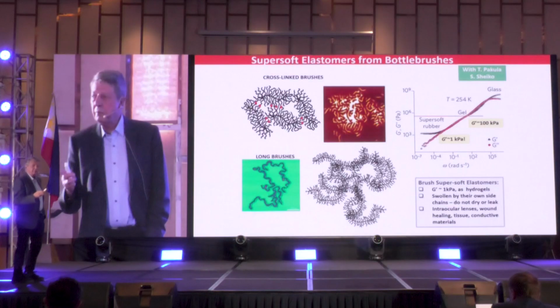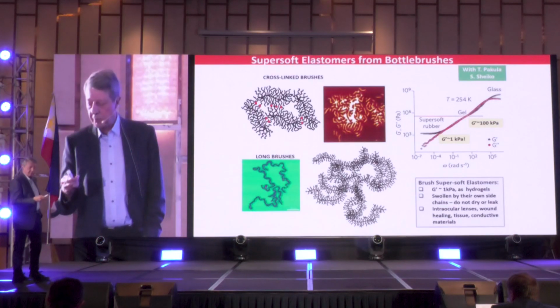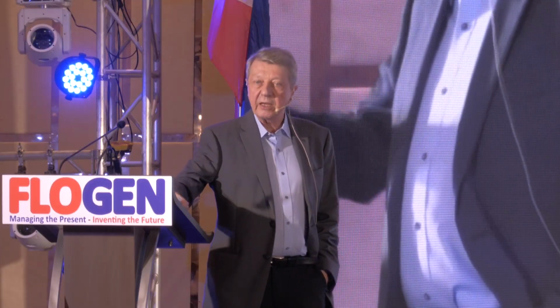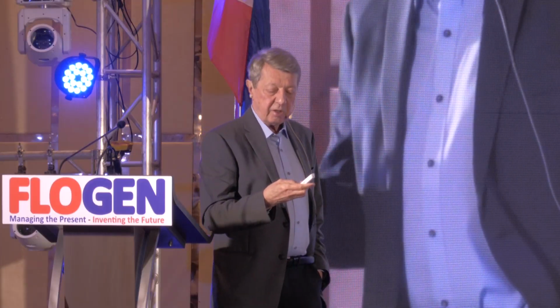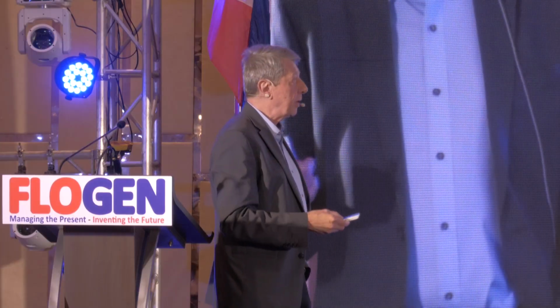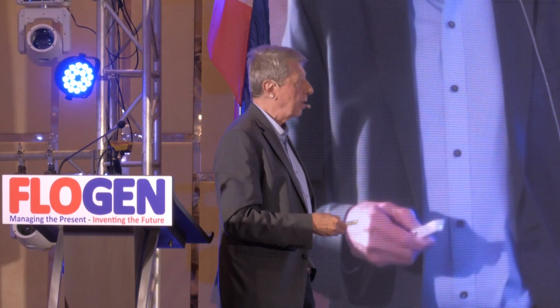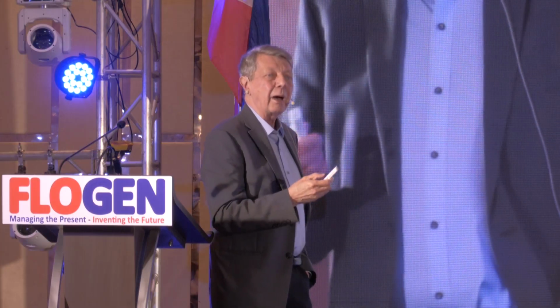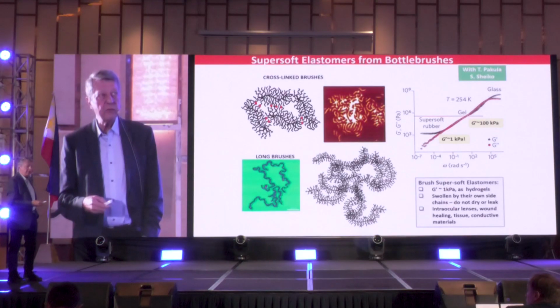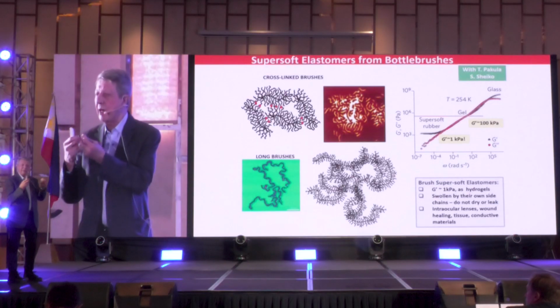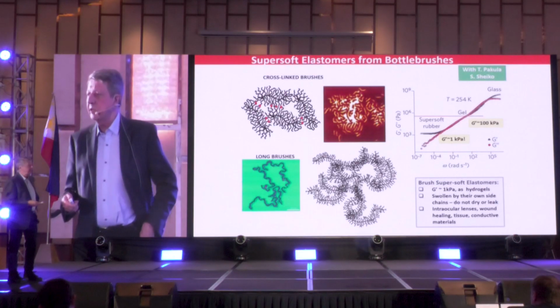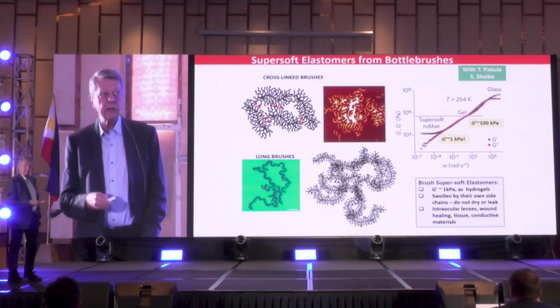So one important issue is the mechanical properties. Every polymer below glass transition is glassy. So it is like plexiglass or polystyrene. It has a modulus in the range of 1 gigapascal. So it would be like this counter table here. But if you go above glass transition, they become much softer. And eventually, they become really like a rubbery material. If you cross-link them, typical rubber, if you think about a rubber band in your fingers, it would have a modulus in the range of 100 kilopascal.